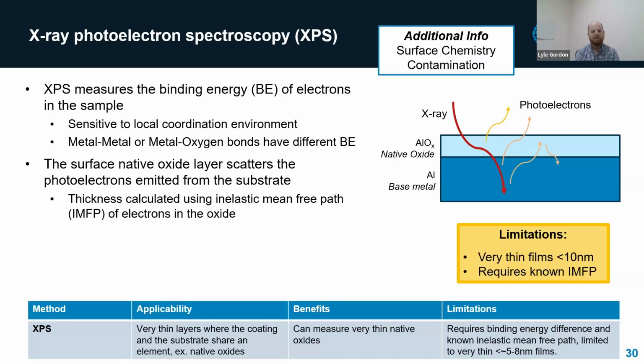So XPS measures the binding energy of electrons in the sample. And these binding energies are sensitive to the local coordination environment. So if the metal is bound to another metal, or if it's bound to an oxygen, they're going to have a different binding energy. And these electrons that we're detecting have to escape from the film. And as the ones from the metal, which is under the oxide, escape, they get scattered by the oxide. And the amount that are scattered and that we don't see, we can use that ratio to determine how thick the film is, because for many of these oxides, that mean free path of the electrons is tabulated and available.